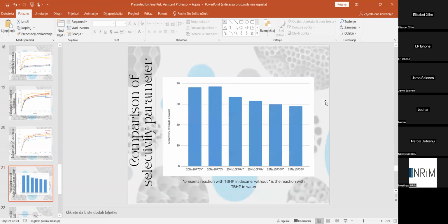Also, we compared the selectivity parameters. Selectivity towards cyclooctene epoxide was compared. Here are the results presented for the TBHP in decane and TBHP in water. So the oxidant was either TBHP in decane or TBHP in water. All the samples with the stars are the samples that participated in the reaction with TBHP in decane. Also, what we can see is that the selectivity for the sample that contains higher content of vanadium is lower than for samples with less vanadium in the structure.